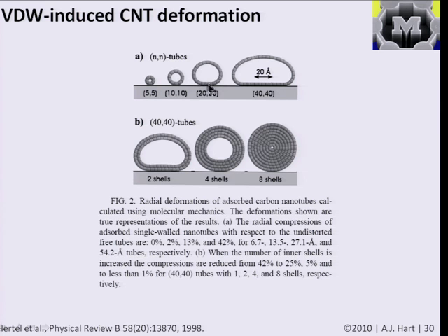these are for single-walled nanotubes, so here the diameter is getting bigger, so it's becoming easier to squash. You can see that because the surface pulls on the atoms all through the tube and pulls down at the sides, and then actually can feel the atoms up above, you actually result in a non-negligible deformation of the tube itself. So if this is a perfectly flat surface, this is actually what happens.